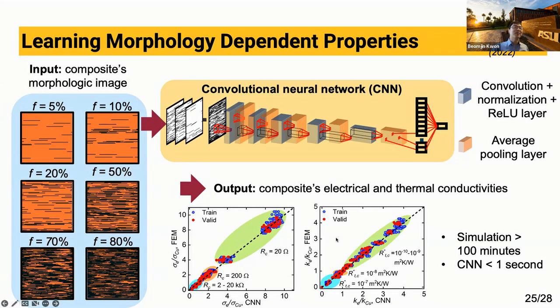And actually preparing the training data took quite a long time, because for the simulation, it took more than 100 minutes for a single morphological image. So if you predict the electrical and thermal conductivity for this single image, especially with the high fraction image, it took more than 100 minutes, I think. So my students took, I think, several days, not just several weeks actually, to prepare all the training data.